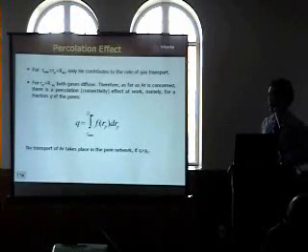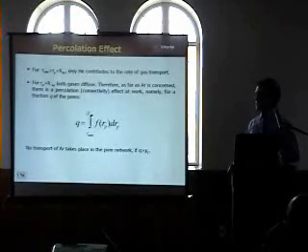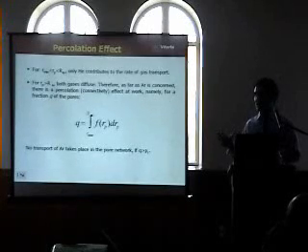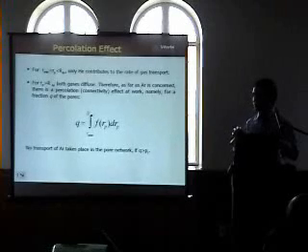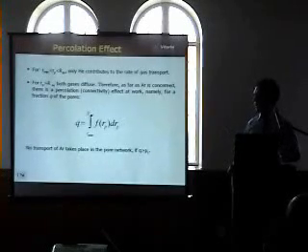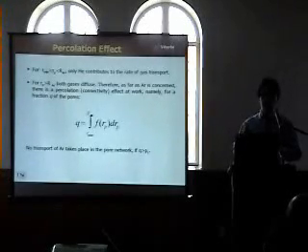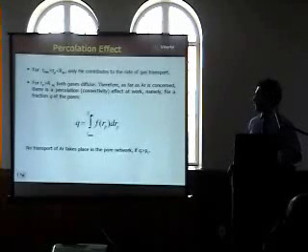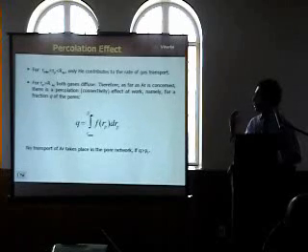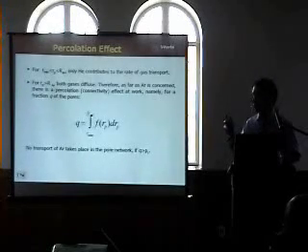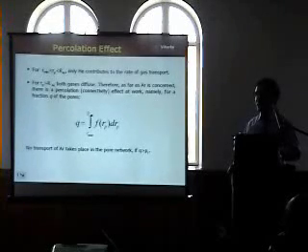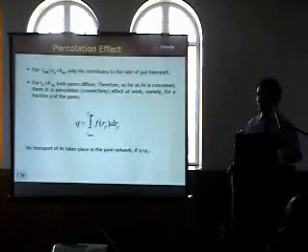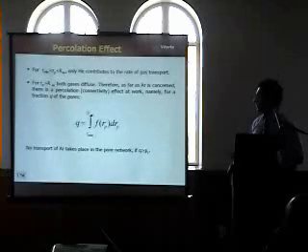So for the argon, for the pore sizes that are smaller than the molecular size of argon and larger than the minimum pore size, which is the helium pore size, only helium can diffuse through our membrane. And for pore sizes larger than argon, both gases diffuse. So as far as argon is concerned, the percolation effect comes into play,